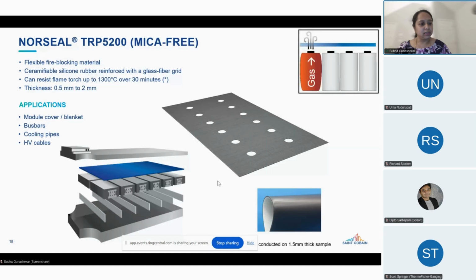And the second one is more like a back cover. It's a solid silicone-based material where many of our customers don't make the cells, so they don't have a cell-to-cell requirement, but they have modules which are put together in a frame. And all that they're looking at is a pack level or a module level cover. So this is a flexible material. It acts as a blanket. Again, depending on the placing of the vent, we can design some ports for the venting gases to exit, or we could have it completely insulated. So this material can withstand temperatures up to 1300 degrees Celsius for over 30 minutes. And this 1300 degrees at 30 minutes was, I think, a 1 millimeter thickness product, but we do offer this product at very thin gauges from 0.5 millimeters to 2 millimeters.